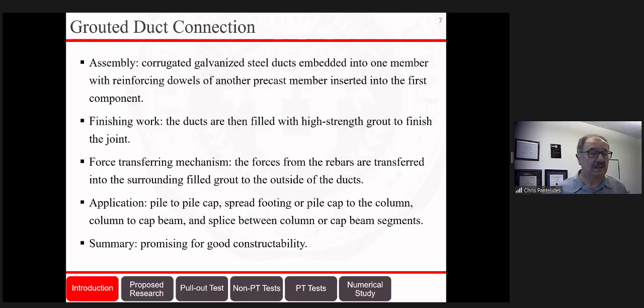So we're using a grouted duct connection, using galvanized steel ducts embedded into the footing, with reinforcing dowels of another member, in this case the column, inserted into the footing. To finish the joint, we fill it with the high-strength grout, which we developed ourselves, as I mentioned. The force transferring mechanism is that the force from the rebar is transferred into the grout and to the outside of the duct. In this case, we used a column to footing connection, but it can be used for many other places and also as a splice.